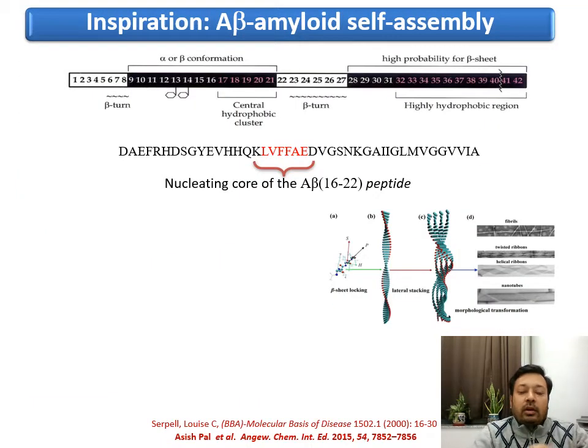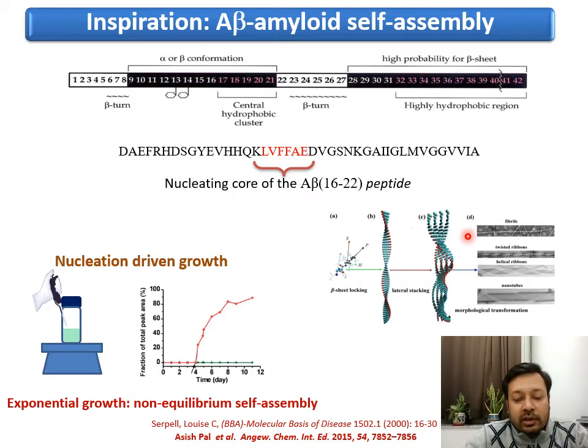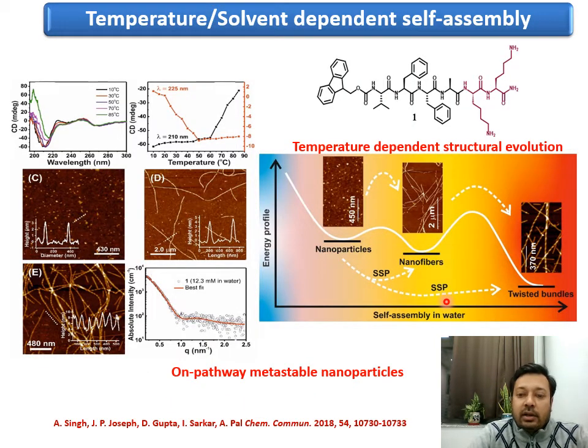So our inspiration has been the A beta amyloid self-assembly, and such amyloid self-assembly happens in a non-equilibrium way, and it can form diverse nanostructures. One characteristic of such self-assembly is that it shows exponential growth. Hence, we designed short peptide amphiphiles where at the N terminus we have a hydrophobic group, and at the C terminus we have a hydrophilic group. With a judicious solvent choice, if you dissolve it, it forms very nice nanofibers and nanoparticles.